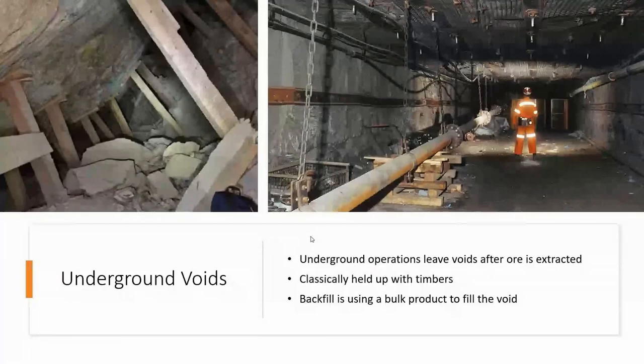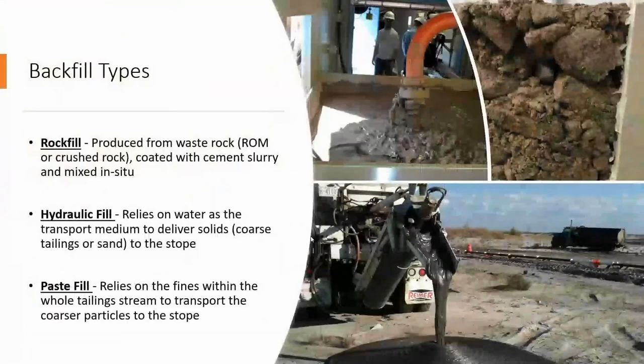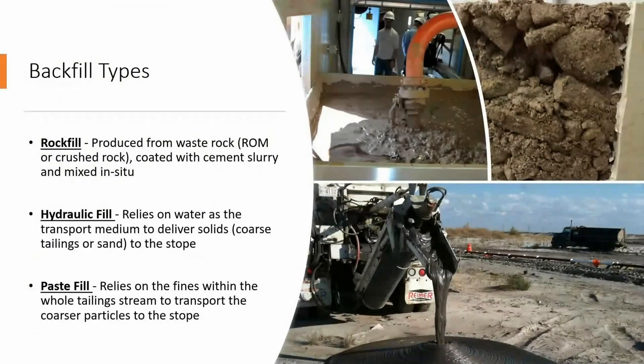Backfill is classified into three types. Rockfill, shown in the top right, is made of coarse waste rock material — this can be developmental waste, ranging in size from gravel up to meters, basically how big you can get in the scoop of a truck. One problem with this is that because you have very bulky angular material, packing is pretty poor. Typically 30% of space in the stope is left as voidage between each rock.